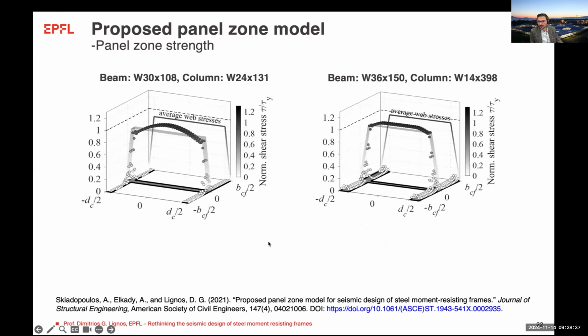Now, with regards to strength, again looking at the mechanics of these panel zones, we split the data we had available into geometries where the beams would be in the range of W30 by 108, and the column would be in the range of W24 by 131. So you would have a panel zone geometry where the aspect ratio is perhaps close to 1.